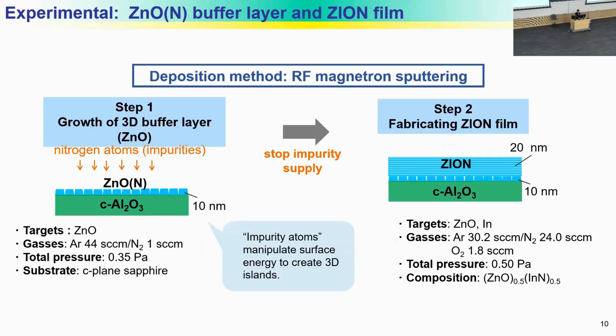Next, I will introduce the experimental method. All films were fabricated by RF magnetron sputtering. The composition of indium is 50%.